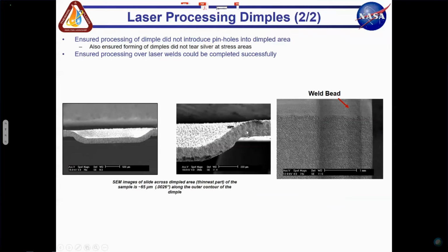We also wanted to make sure that we weren't punching through the dimples. The thinnest section on the sheet is the area where that transition of the dimple occurs. So UNL did some amazing work, and they actually sliced one of the dimples in half and SEM'd the cross section of it. This is a picture of the dimple sliced in half. The middle picture is zoomed in on specifically that transition. It has laser processing on both the positive and the negative side. And as you can see, there's still meat in the silver, so we're not punching any holes through there.